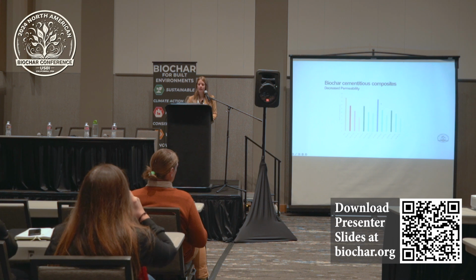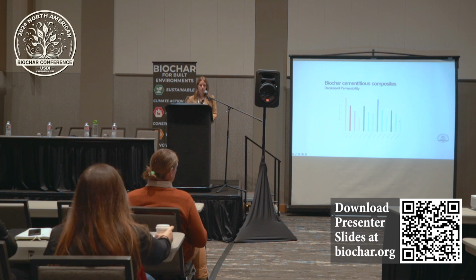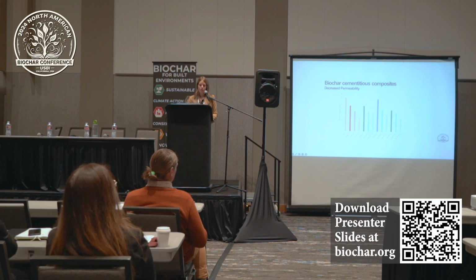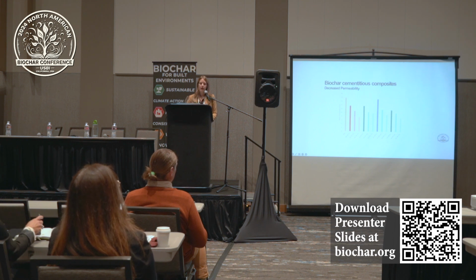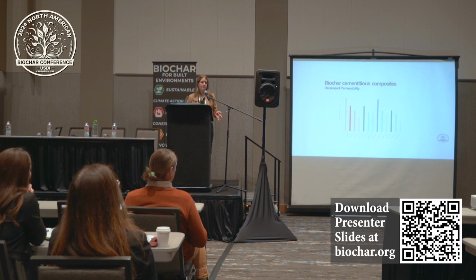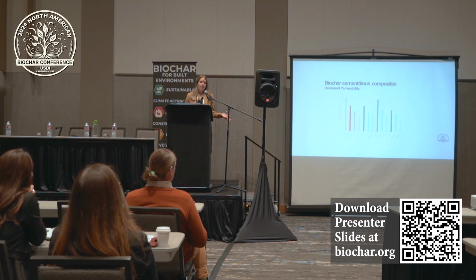biochars here tested and at 3 different concentrations. So we've got a 5% replacement, 10% replacement, 15% replacement. You can see each biochar affects the permeability a little bit differently, but consistently we see a decrease in permeability with increasing biochar replacements. The implications of this are huge.